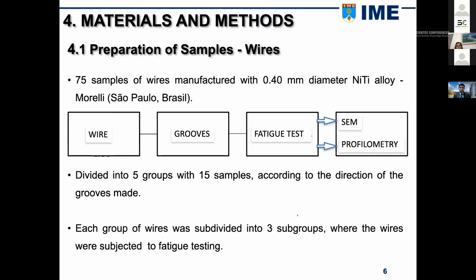Materials and methods. Preparation of the wire samples. The surface of the orthodontic wires was manually polished with silicon carbide sandpaper number 220. The samples were separated into 5 groups, each group with a different groove direction. Grooves were made in the following directions: longitudinal, 36, and 90 degrees. In the 5th group, samples without grooves were used.